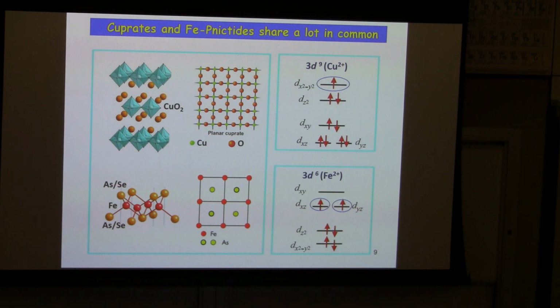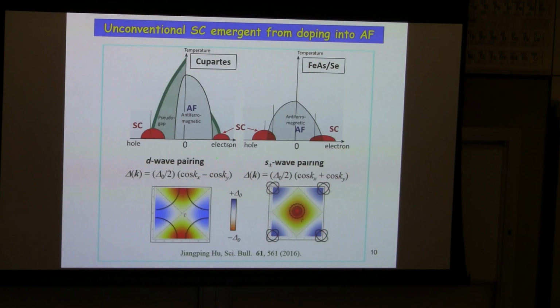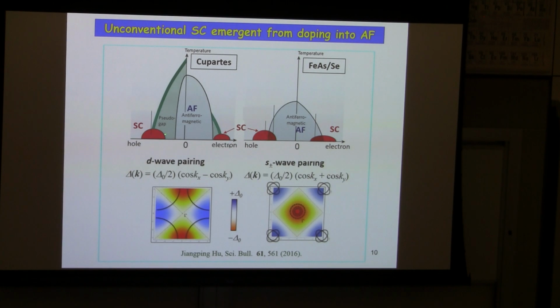And also, as I already said, in this configuration there is some vacant or singly occupied state. In the cuprate case, the dx²-y² orbital is singly occupied. In the case of iron 2+, two orbitals are singly occupied. Of course, this isolated electron has a localized spin, so the starting material is always antiferromagnetic, and we need doping to get superconductivity. That is also the case.